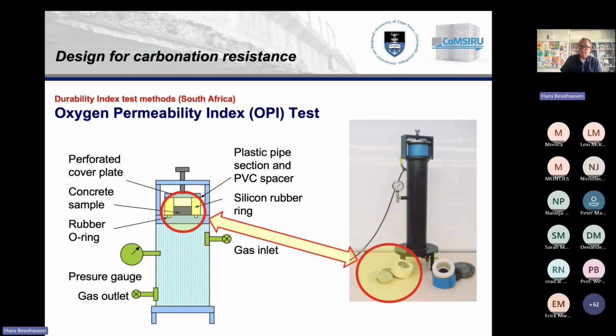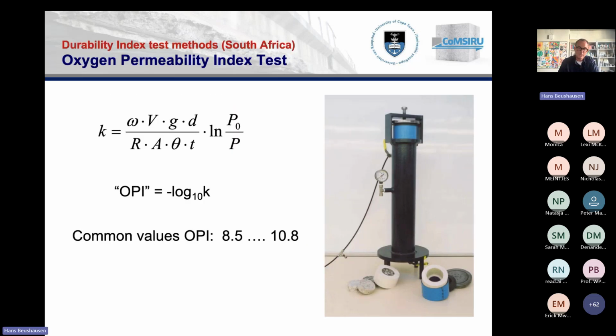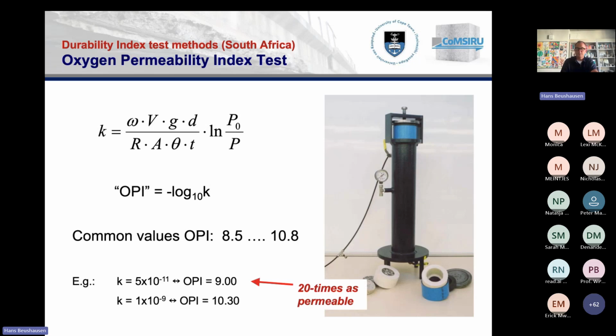And of course, the more dense the concrete is, the slower the oxygen will progress through the concrete, and the lower the permeability will be. So we essentially measure the permeability of the concrete under an applied gas pressure. And we interpret the resulting coefficient of permeability, which is calculated with this ugly equation there, in terms of the negative logarithmic value of that coefficient. What that means is that we express the coefficient of permeability in values typically between 8.5 for poor quality concrete to 10.8. But this being on a logarithmic scale means that one order of magnitude is given if the OPI increases or changes by 1.